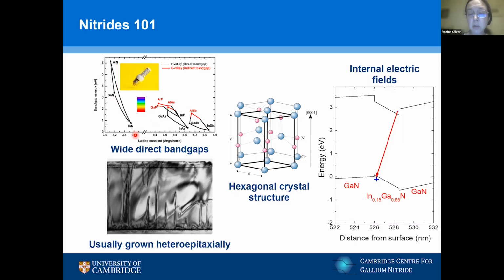A material like gallium arsenide, you'd be able to buy as a large single crystal or a large single crystalline wafer. That's difficult still in the nitrides. There are increasing amounts of bulk material available, but it's very expensive and hard to come by. So we grow almost all our commercial devices heteroepitaxially on unlike substrates, most commonly silicon, sapphire, or silicon carbide. That means that because of the difference in lattice parameter between the substrate and the device grown on top, you tend to get a lot of defects in these materials. These defects are dislocations, line defects, which run straight through your whole nitride film, sort of threading through your device. We call them threading dislocations.